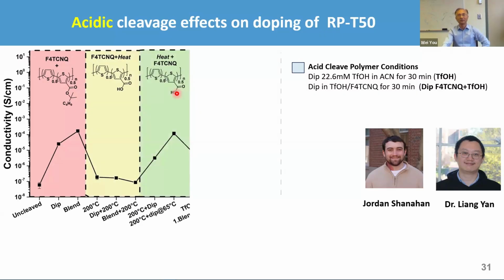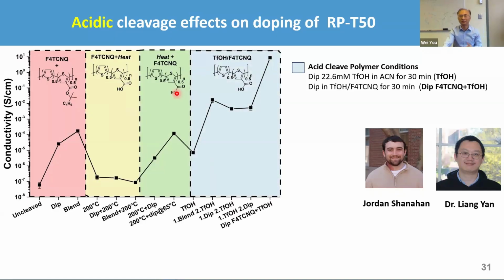Not much conductivity, and again, not much happening because of this thing. But once you use the triflic acid to remove the side chain at room temperature, something magic is happening. You see, when you blend, the triflic acid is also an oxidizing reagent, so it has some doping effect. If you put in the triflic acid together with F4TCNQ, if you remove them first, remove the second, you see some leveling off. You don't see much conductivity difference.